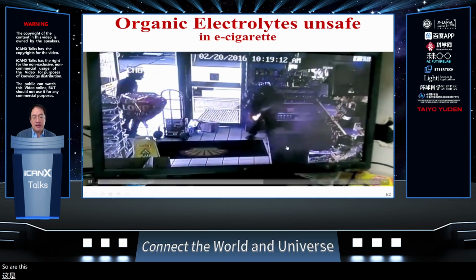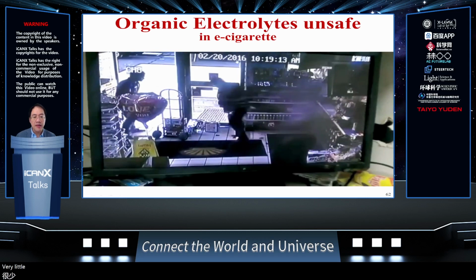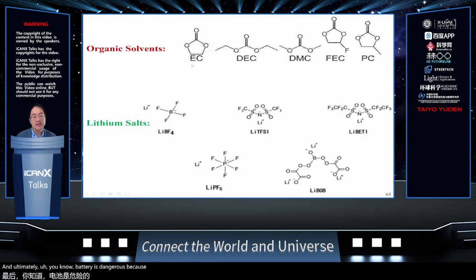So this is from a cigarette-sized, very little battery in the electronic cigarette. Unfortunately, this guy was not hurt. And ultimately, battery is dangerous because inside you have these organic solvents, which are volatile. So they have high vapor pressure, but also your cathode material, these transition metal oxides, when you charge them to high voltage, they themselves can release oxygen. So they don't actually need external air to burn. There's a lot of fuel in the battery electrolyte and in the anode, but the cathode has its own oxygen. And so very often you have something called a thermal runaway, which is initially very small, maybe just a few microns in size, but that gradually self-amplifies until you have this eventual explosion, you breach the packaging and you have a big explosion.